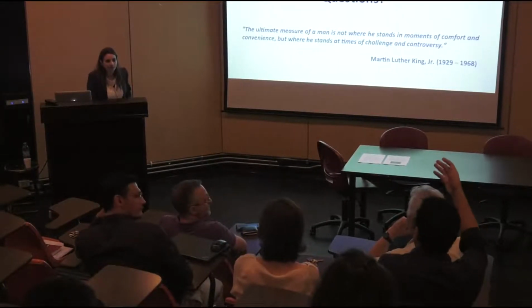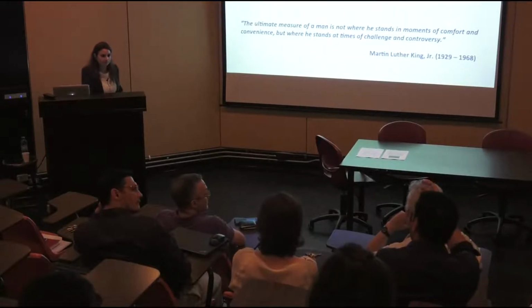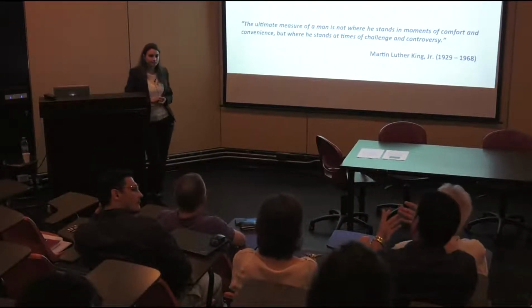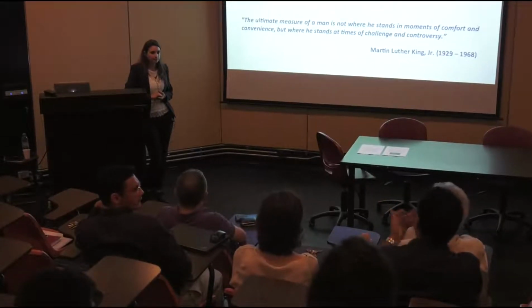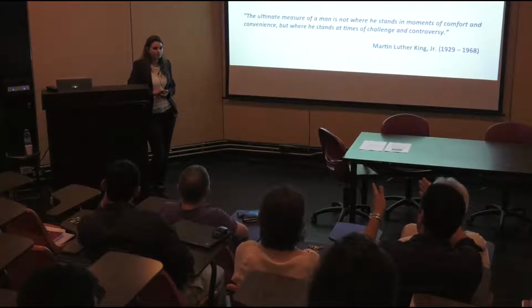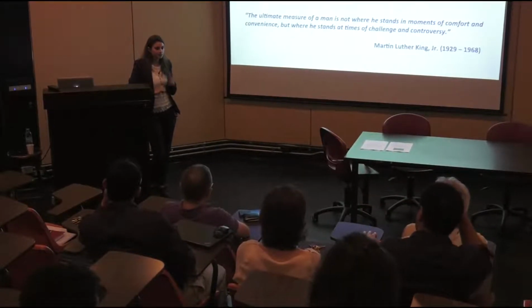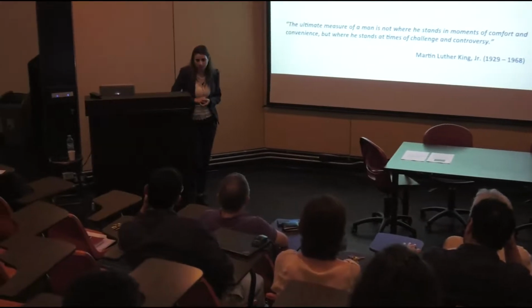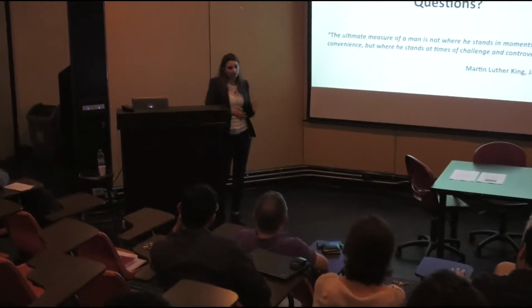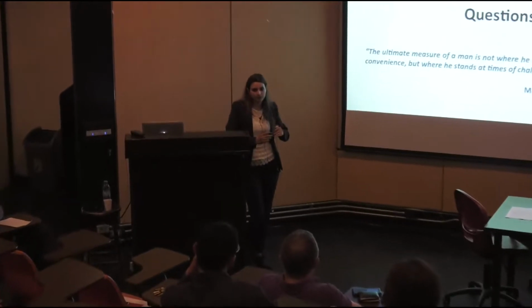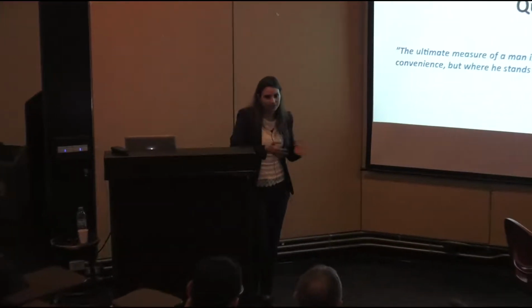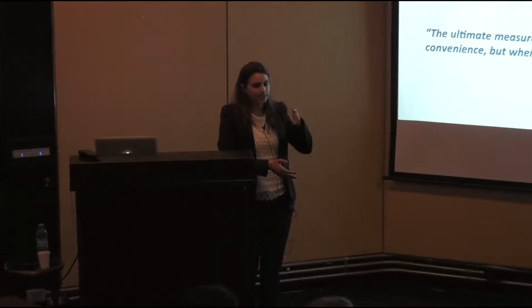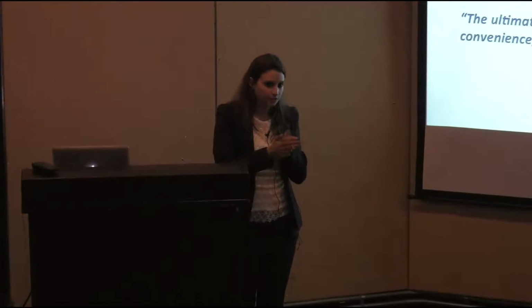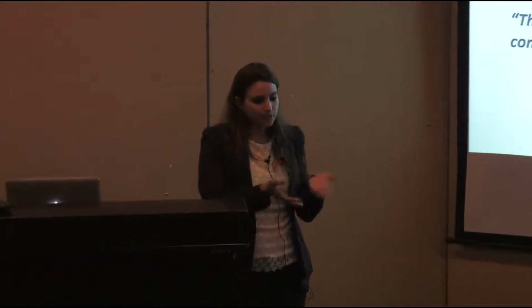And I want to quantify the benefits of using this phase change material inside the plexiglass. How much energy or insulation would I gain compared to air, if I look at a double glazed window with air in between versus with Octadecane? Well, the latent heat of fusion of Octadecane is 250 kilojoules per kilogram, so it's very high. Air doesn't have one, because air is not a phase change material. But what is important is that, because of this melting and solidification, it can absorb the excess heat and increase the thermal capacity of the wall or of the glazing.